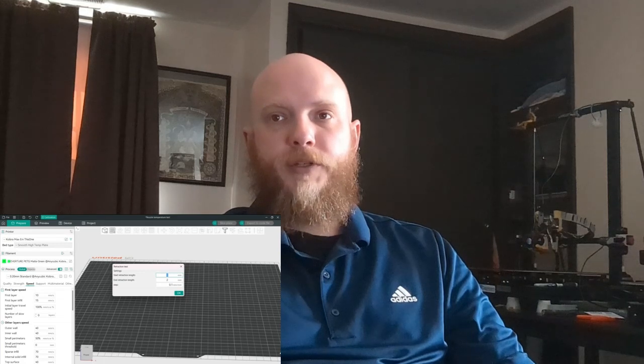A dialog box will appear where you can input a starting and ending retraction distance, along with a step value. What this does is print two small cylindrical towers side by side. Every few layers, the amount of filament retracted will increase by the specified rate. Once the test finishes printing, examine it closely. The goal is to find the layer with the least amount of stringing between the two towers. When you find the cleanest layer, count up from the bottom to determine which step it's on. Multiply that number by the retraction step size you chose earlier, and you'll have your ideal retraction setting.